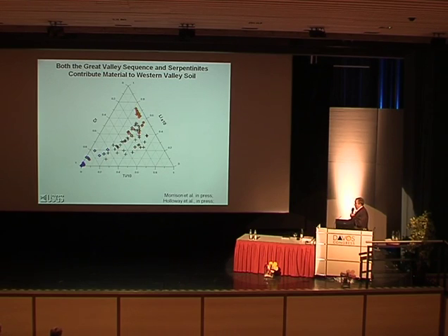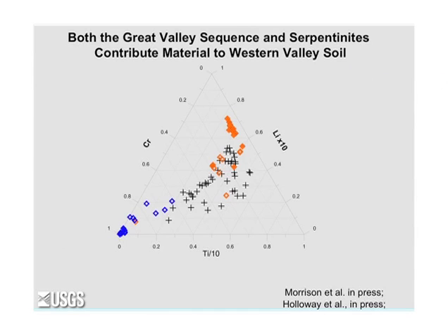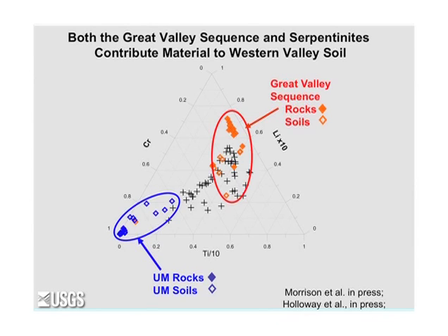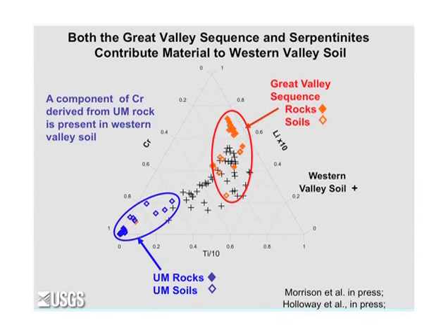So this is a triangular plot in which titanium, which we use as sort of an immobile element, goes from 0 to 1 on a normalized scale. Lithium from 0 to 1 on this axis, and chromium on 0 to 1 on this axis. Ultramafic rocks and the overlying soils plot at the chromium end of the diagram with very low titanium and very low lithium. The Great Valley sequence rocks and their overlying soils fall towards high lithium, high titanium, and low chromium. The valley samples, and these are all soils from the western Sacramento Valley, fall on something of a mixing line between the two. The important point is that a component of chromium is derived from ultramafic rock and then transported down into the valley.